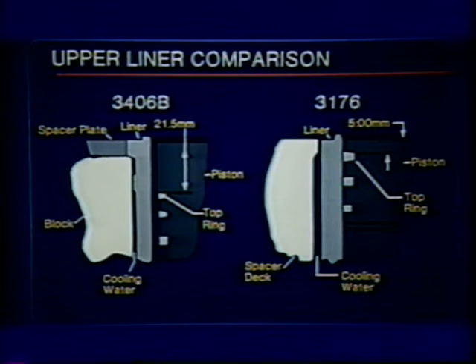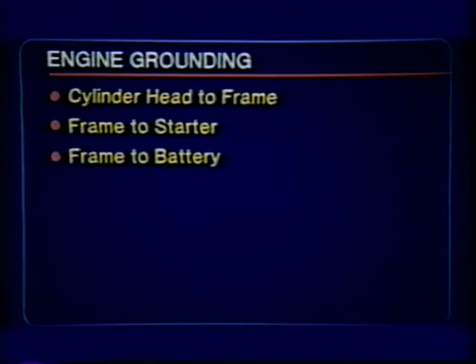The microstructure and alloy content of the aluminum spacer deck is closely controlled to guard against galvanic damage. The spacer deck utilizes a low copper alloy aluminum to inhibit the conduction of stray electrical currents, which can cause galvanic corrosion. Aluminum is prone to galvanic corrosion only when the engine is improperly grounded or coolant recommendations are not followed. Any potential for corrosion in the 3176 is controlled by grounding the cylinder head to the frame to the starter, and the frame to the battery.